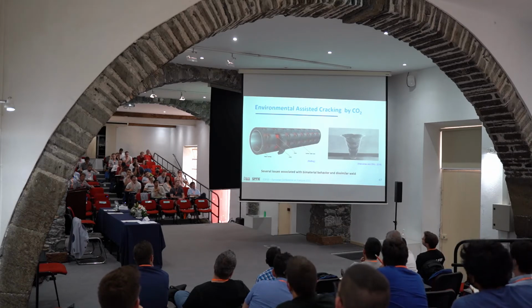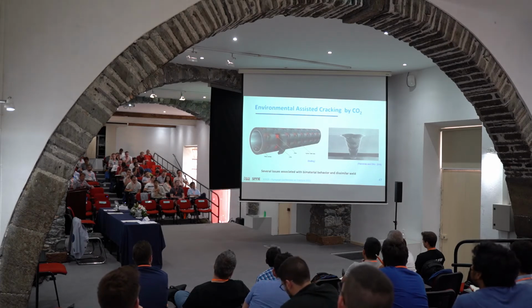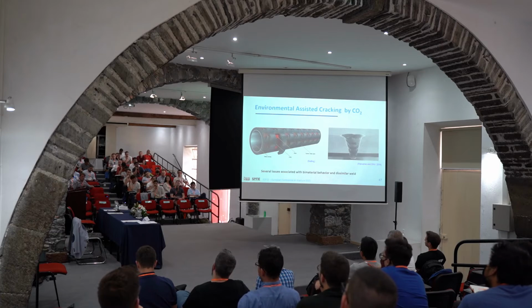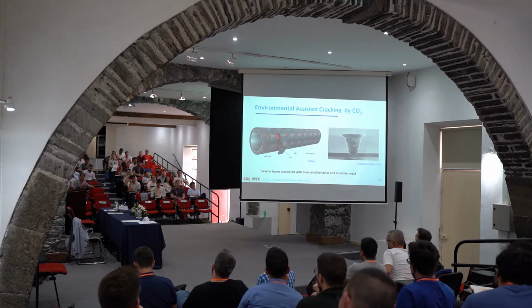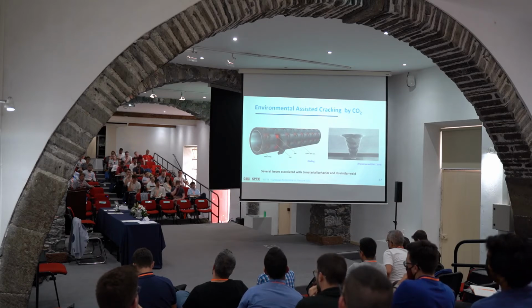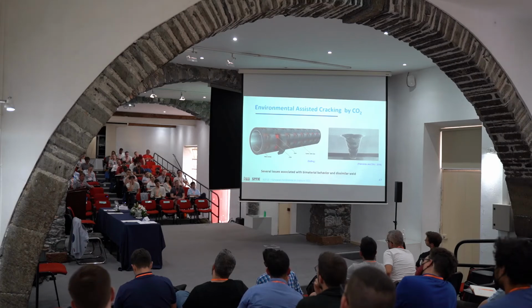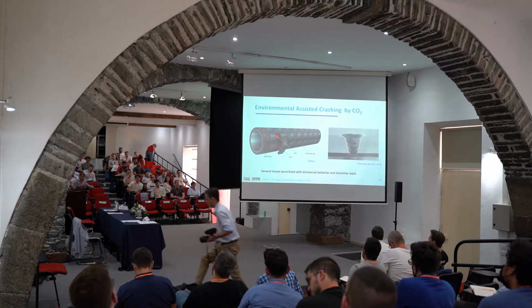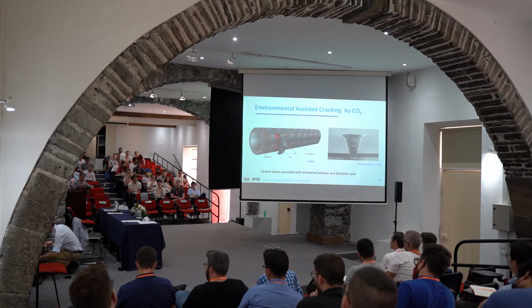And because of this, the new generation of pipes is actually lined inside with a very expensive Inconel layer. Nickel, chromium, not standard stainless steel, 316, 304. It's Inconel 625, with high nickel, high chromium, very expensive. Because it's very expensive, usually what we do is the outside pipe, which should resist the pressure, is standard pipeline steel, X60, X70, and the inner side is usually a 3 millimeter layer of Inconel 625. However, the pipe in itself is fine. There are many technologies of lined Inconel pipes, from a German-based company. I think it's a boutique or something like that.